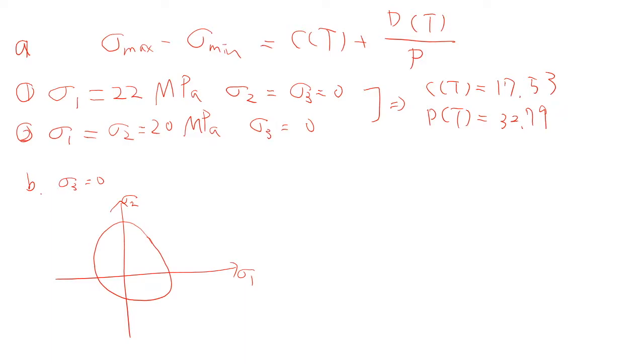If I got a circle, this means that if I have stress higher than this, I will start shear banding. And for the crazing criterion, I get something like this. In this case, if I have higher loads, then I will start crazing, for the crazing criterion, which are the two lines I was drawing. So, for example, if I have a sigma 2 load that is higher than this value, then I'll start crazing instead of shear banding. So you can examine the criteria after you get the values and try to draw the graph like this.